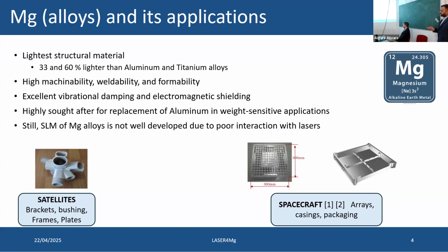These two sectors are highly seeking to produce parts like these from magnesium alloys. In particular, this part is a thermal part that goes on a satellite, and they were able to achieve 20% weight reduction with similar mechanical performance. Also for spacecraft arrays, where these are used with the sensors and everything, they were able to achieve up to 25% weight reduction with similar performance. These kinds of parts are much easier to build with 3D printing than with conventional machining. So that adds to why the laser interaction of magnesium alloys should be studied more.